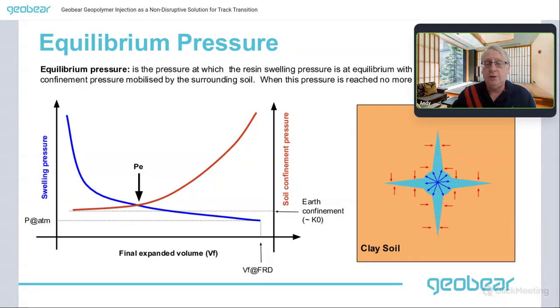This shows the relationship between the swelling pressure and the soil confinement pressure. As the geopolymer expands in the soil, there's a resisting force from the surrounding soil. Where those two pressures are in balance, you establish what's called the equilibrium pressure, and that's the point at which the geopolymer hardens in the soil. If you know the equilibrium pressure or can calculate it, it allows you to calculate the in situ density of the geopolymer, from which you can calculate its strength, and from which you can calculate how much ground improvement you're going to get. So determination of equilibrium pressure is a very important part of the design process.